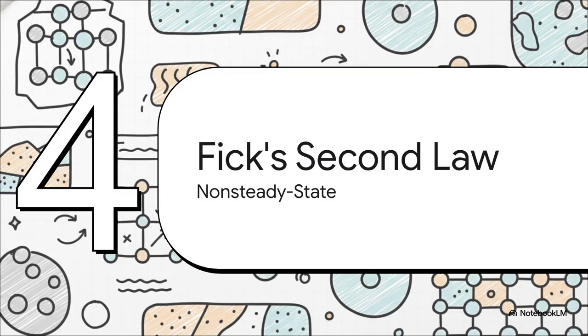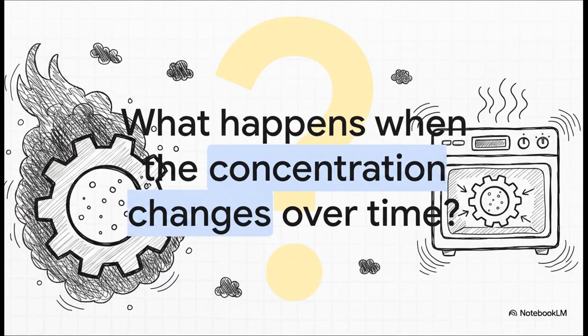Let's move to section 4, Fick's second law, non-steady state. Ask yourself this: what happens when the concentration is constantly changing over time? Like when you throw a solid steel gear into a hot oven filled with carbon-rich gas to case harden it, the carbon doesn't just flow completely through the gear and out the other side, right? The carbon enters the surface and stops inside, meaning the concentration is shifting every single second.